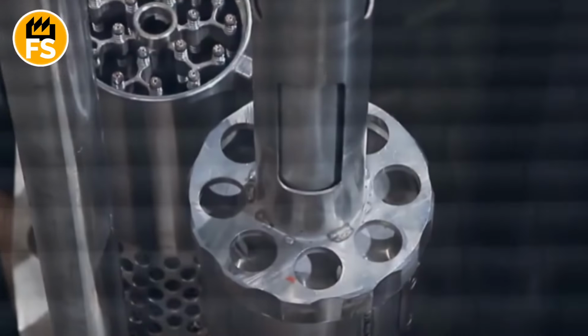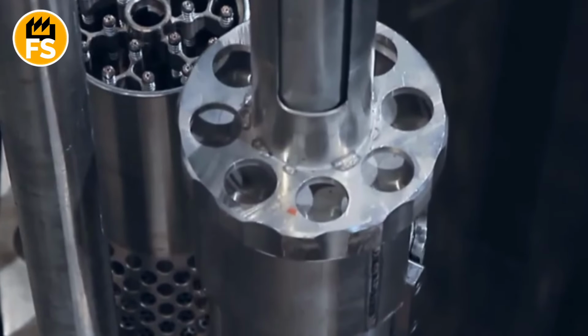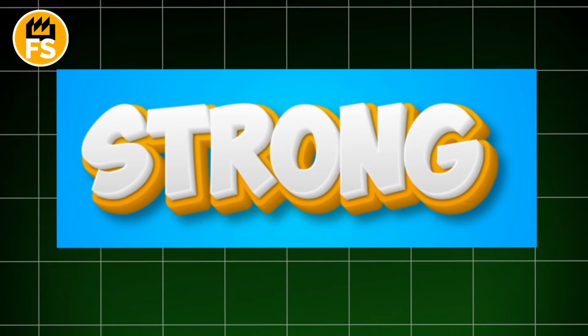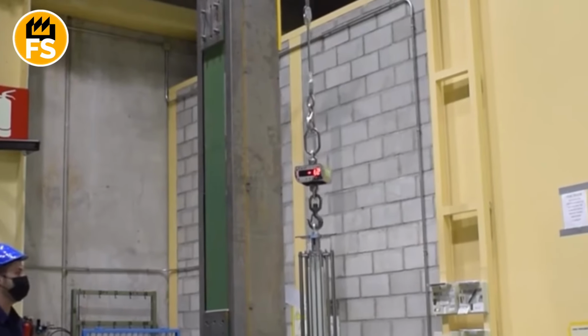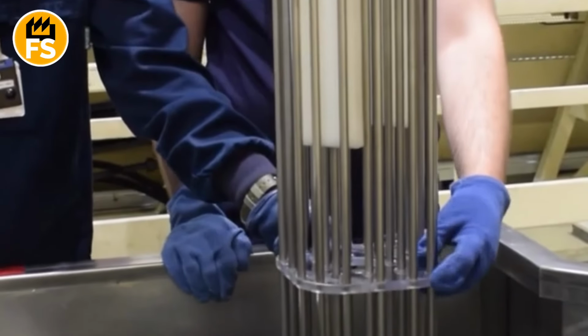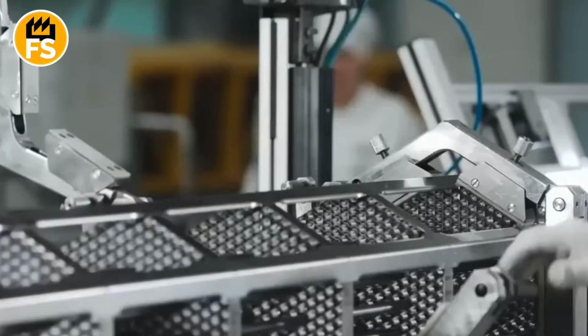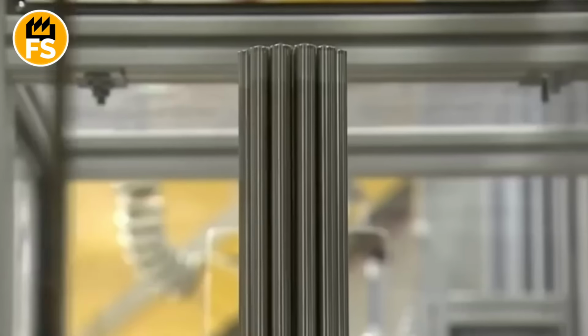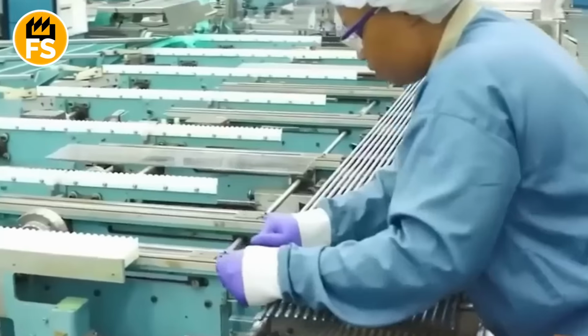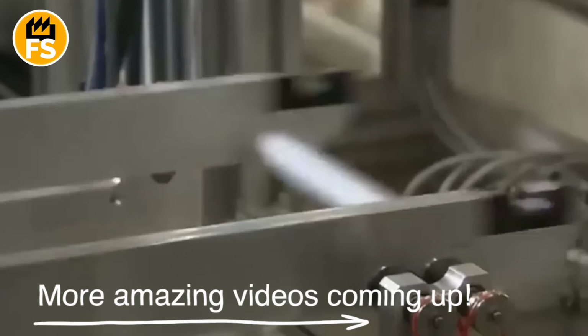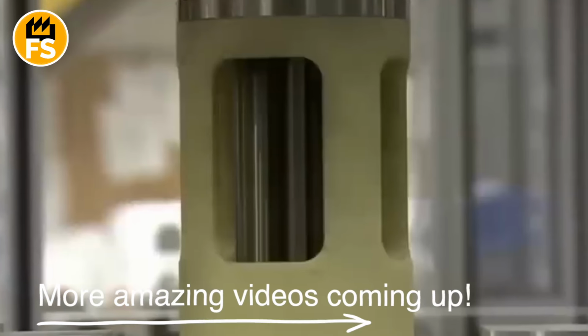These tubes, about 13 feet long, are not made of steel, but of a special zirconium alloy called Zircaloy. This material is unique in that it is very strong, resistant to corrosion, and most importantly, almost transparent to neutrons, allowing the chain reaction to proceed without hindrance. When the tube is completely filled with pellets, it is filled with an inert gas, usually helium, to improve heat transfer, and hermetically sealed at both ends. Now, it is not just a tube with pellets, it is a fuel element.